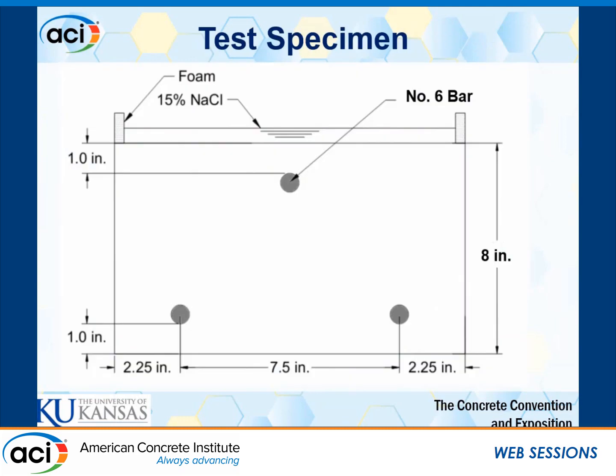If you're looking at settlement cracking by itself, here's a diagram of one of our test specimens. All you really need is that top number 6 bar in our forms. So that'll give you the data you need after you pour the concrete over that, allow it to set, and then you can measure the crack length and width over it.